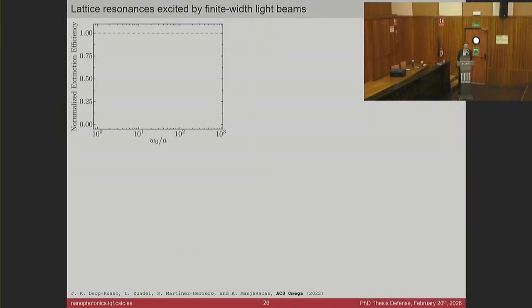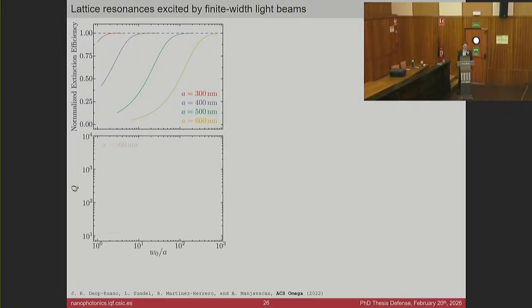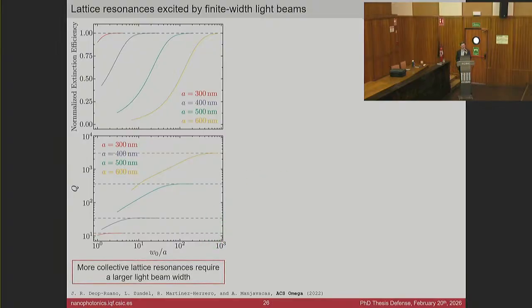We can analyze this in more detail by plotting the peak extinction efficiency, normalized to the plane wave limit, and we see that for increasingly collective arrays with higher period, we need a larger and larger beam width. The same happens for the quality factor. We see that as we increase the period, the quality factor of the resonance increases, but to actually see this quality factor, we need increasingly large beam widths.